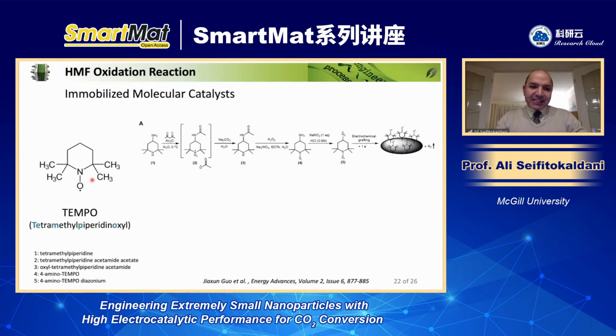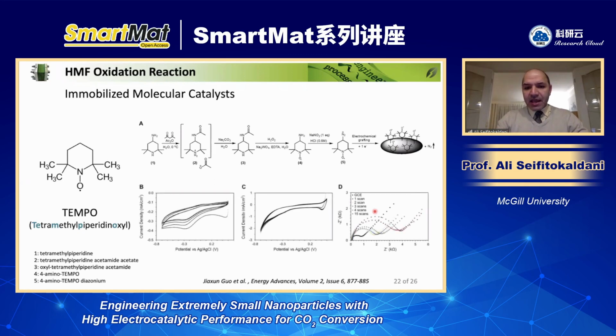Immobilizing TEMPO itself is not really an easy job. So we went through a little bit complicated chemistry procedure, but eventually we were able to functionalize the TEMPO like this one. And then through the electrografting procedure, we immobilized that on the surface of different supports such as carbon felt, graphite, and also glassy carbon rod. The electrografting system is quite simple. You just run a CV for a few cycles. You need to optimize it, and to optimize it, we were using EIS or a frequency response analyzer to understand how many cycles we require to have the optimum surface coverage of the TEMPO.